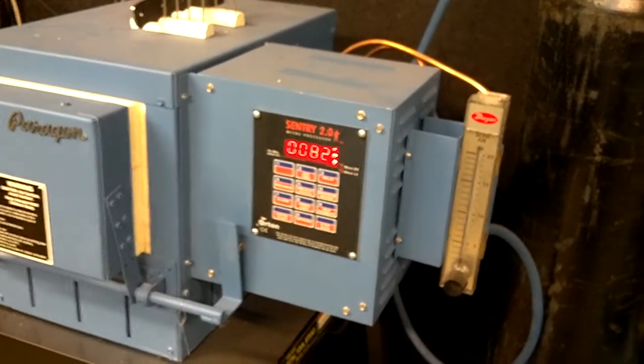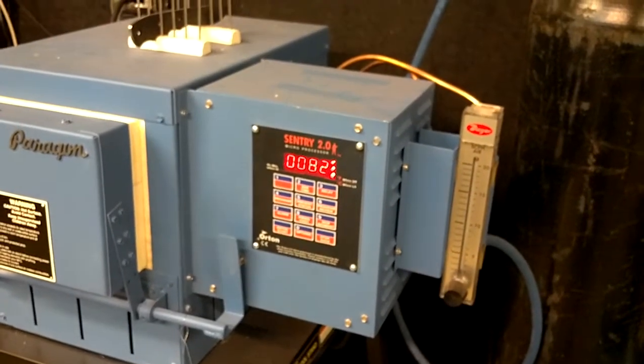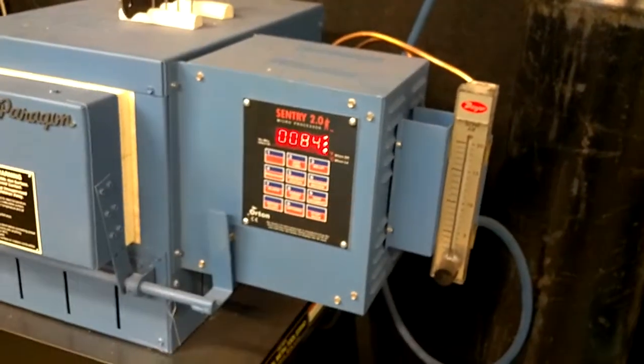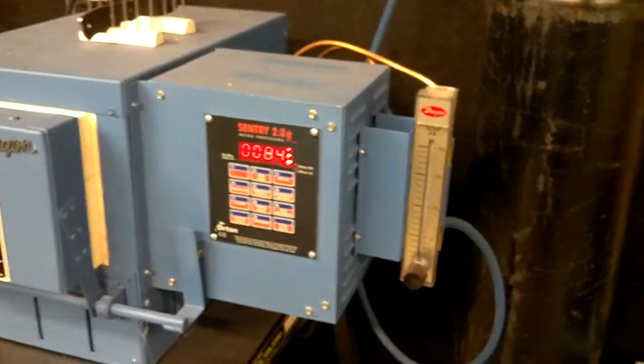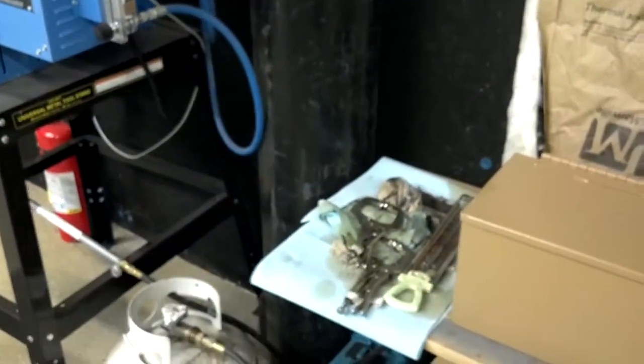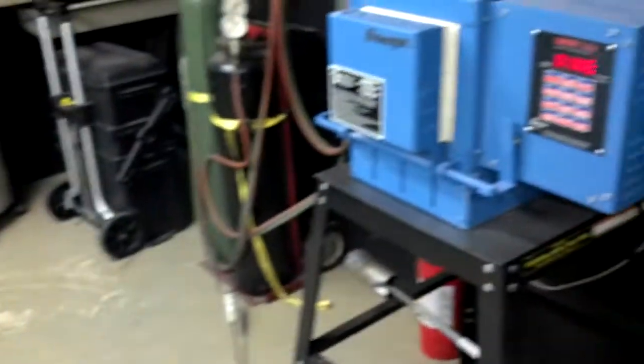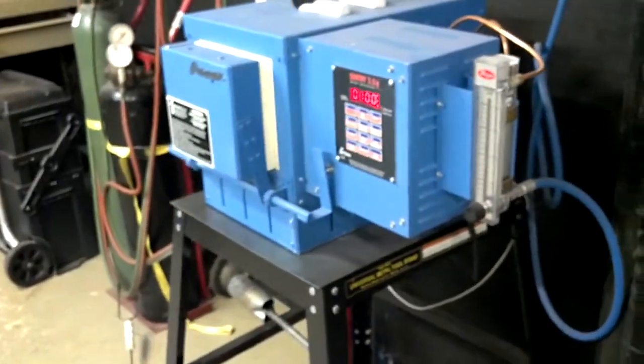So we've got this kind of firing climbing and it's going to be a little while before we are ready for the quench. Once it starts getting close I will get this oil heated up a little bit over here, get it to about 150 degrees. And then like I said we're going to pull it out of the oven, quench it until it just isn't red anymore, take it out of the oil and then air cool it down to equalized temperature of the room.